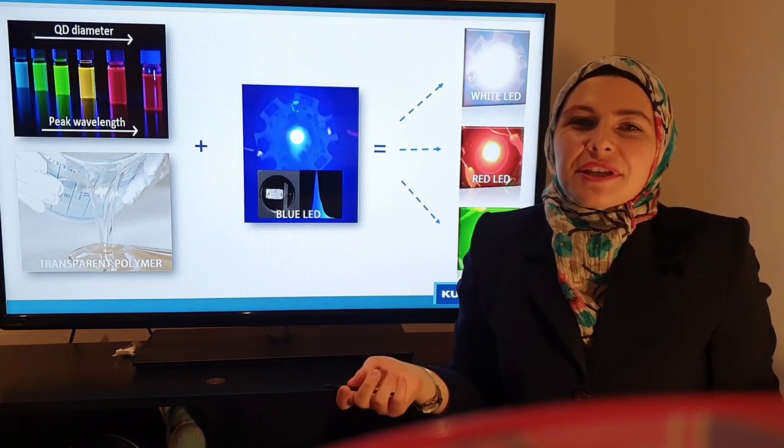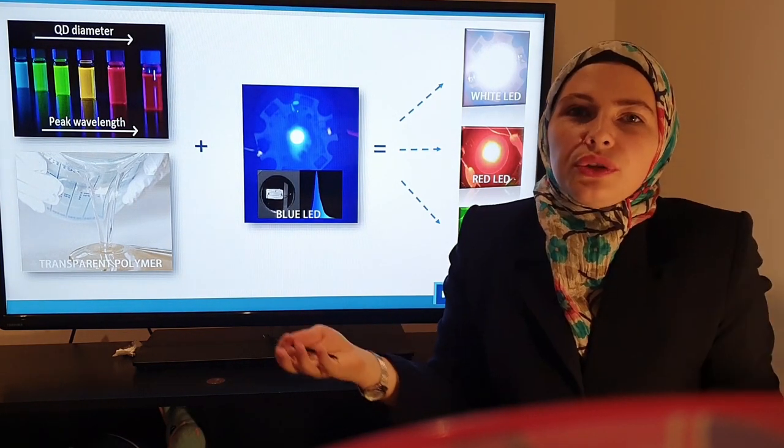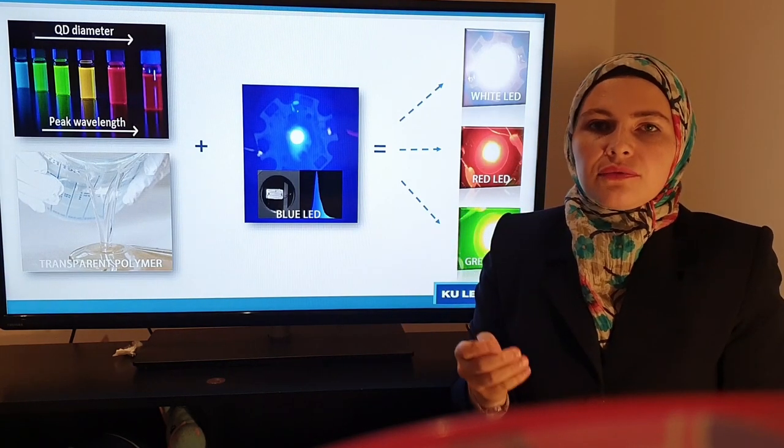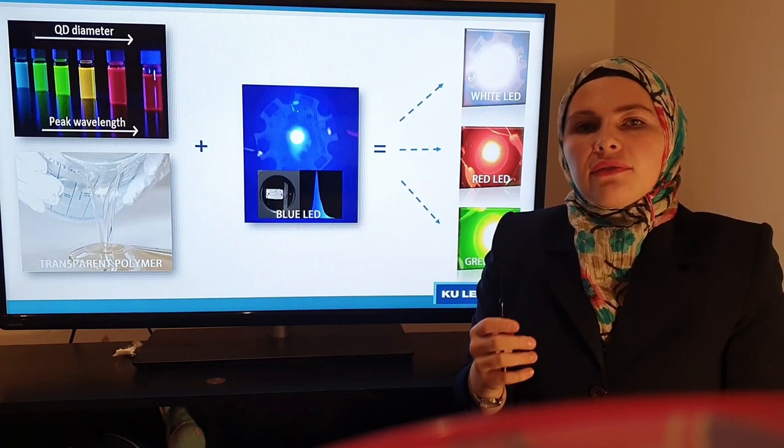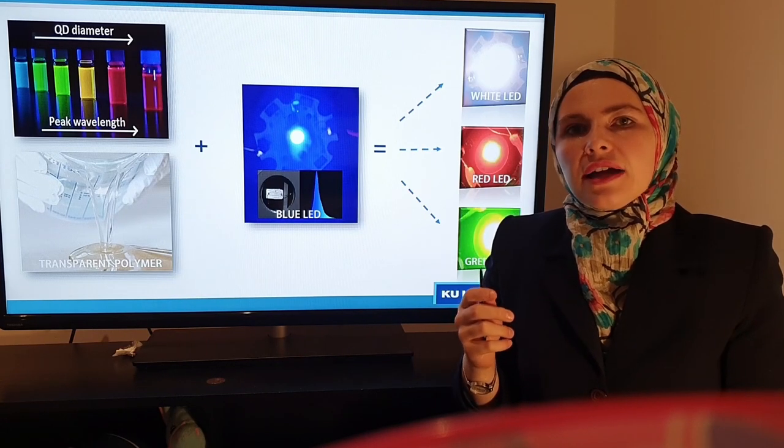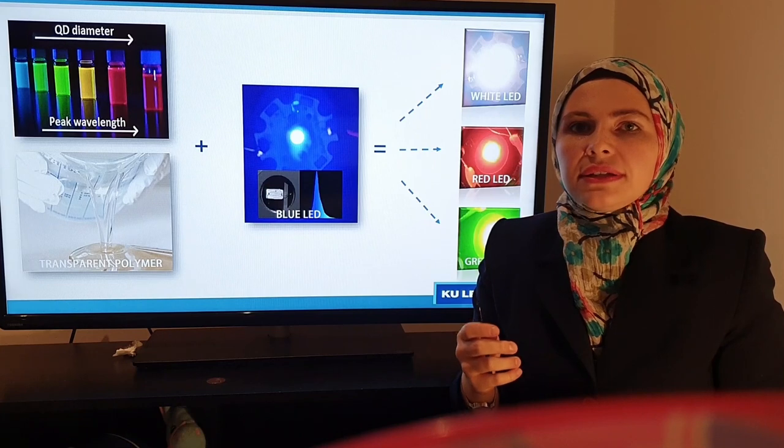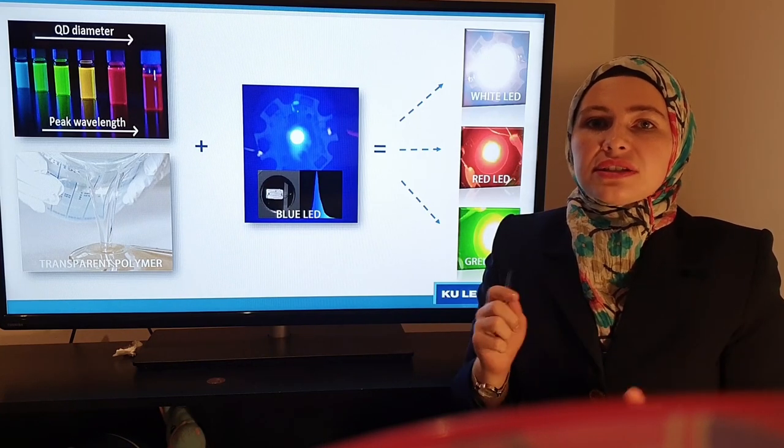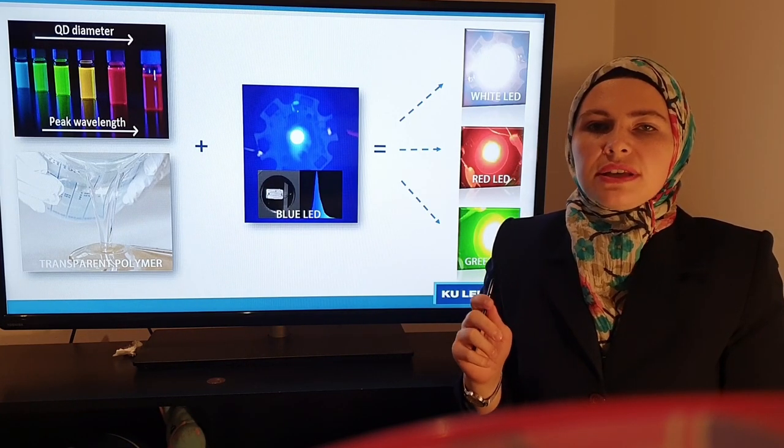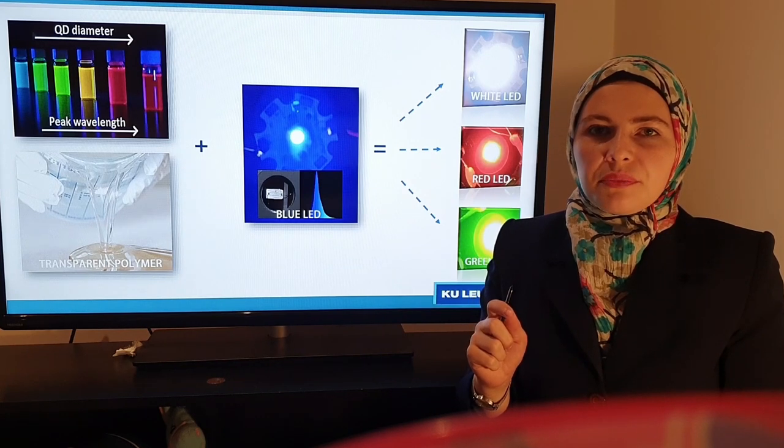In fact, I am experimenting on how to make good LEDs using indium phosphide quantum dots. For example, we have already developed a high performance white LED, which has high color rendering ability and its spectral efficiency is only 4% lower than its cadmium based opponent currently available on the market.